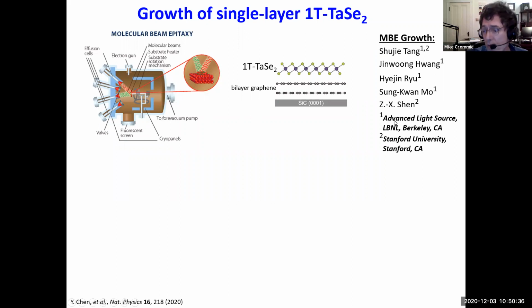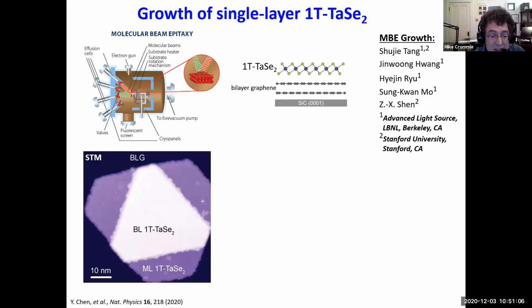Our samples were grown in collaboration with Zhi-Xun Shen's group at Stanford and Sung-Kwan Mo's group at the Advanced Light Source. Sung-Kwan Mo is a beamline scientist at the Advanced Light Source in Berkeley. They grew the material using MBE. Basically, they took a wafer of silicon carbide and heated it up in UHV to grow bilayer graphene, and then they used evaporators to grow the 1T TaSe2 on top in monolayer form. Then they gave the sample to my group to look at with STM. And here you can see a typical STM image of this material.